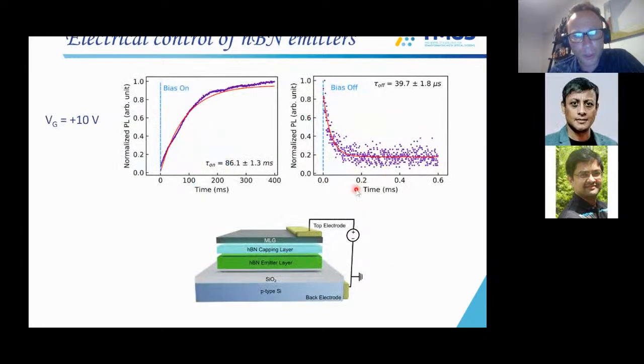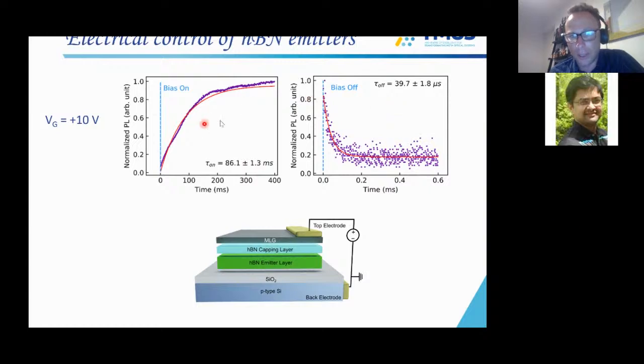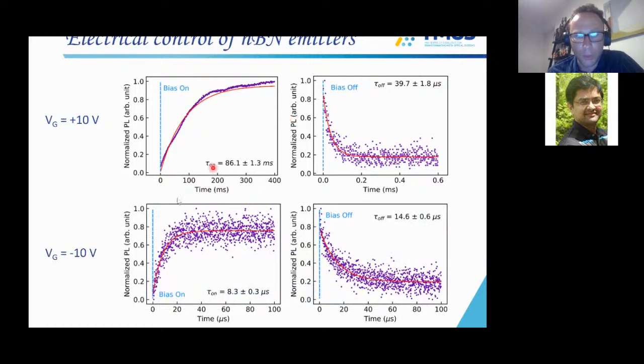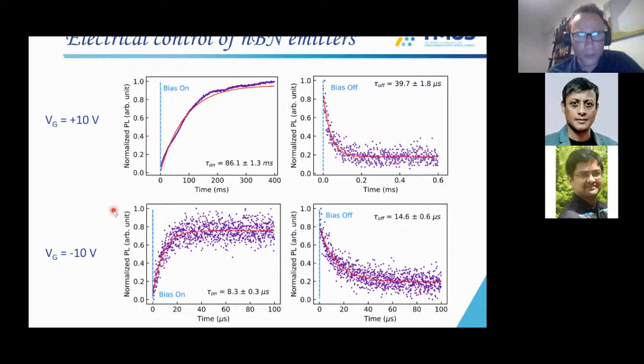So we looked into this in more detail, and you could see that when we turn on the voltage, the rise time to see the luminescence is very slow. It's about 80 milliseconds, but the bias off is about several tens of microseconds. So you can see that the mechanism between the on and off is different, and I will come back to this in a few slides. And when you apply negative bias, you see very fast on and very fast off. So that already tells you that the positive and negative biases induce different mechanisms for this emission. So we looked at this further.